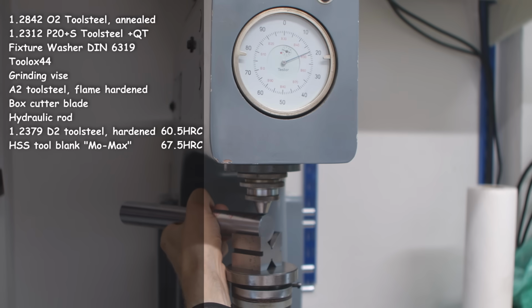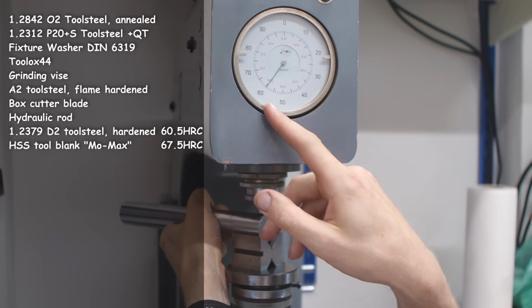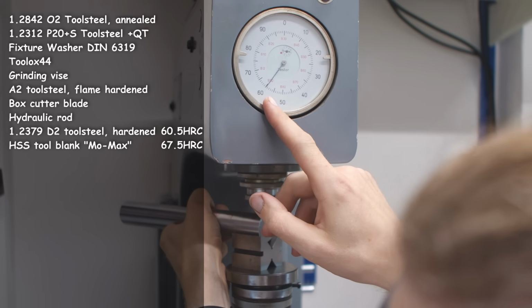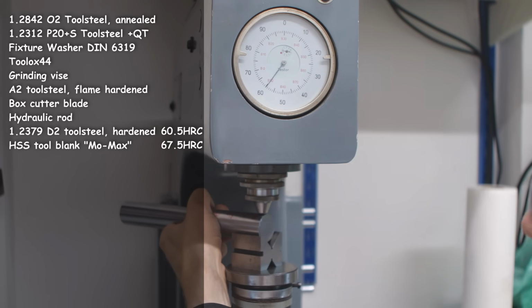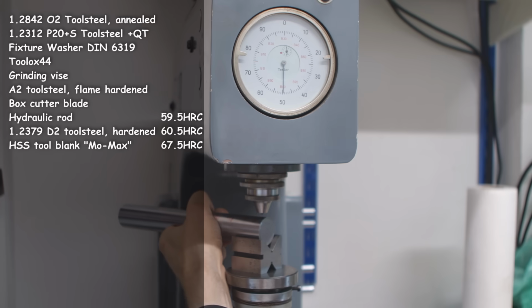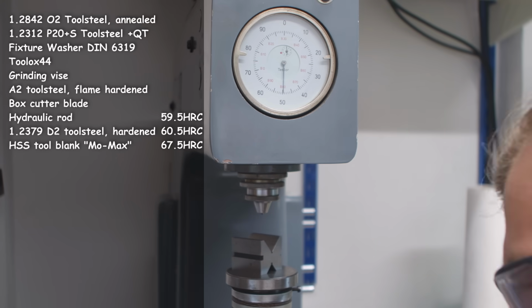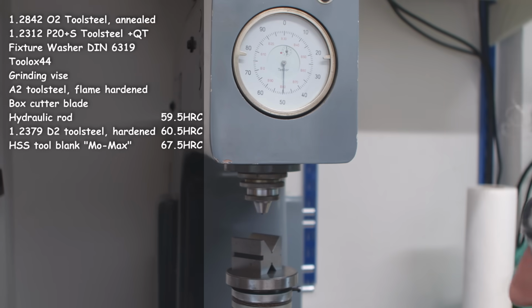And I know for a fact that the hydraulic rod is fairly hard. That's a combination of the case hardening and the chroming. We get a little bit under 60 Rockwell C. So this is quite a nice material to make things out of. You just have to be careful because it's far from round. Hydraulic rod tends to be fairly non-round.